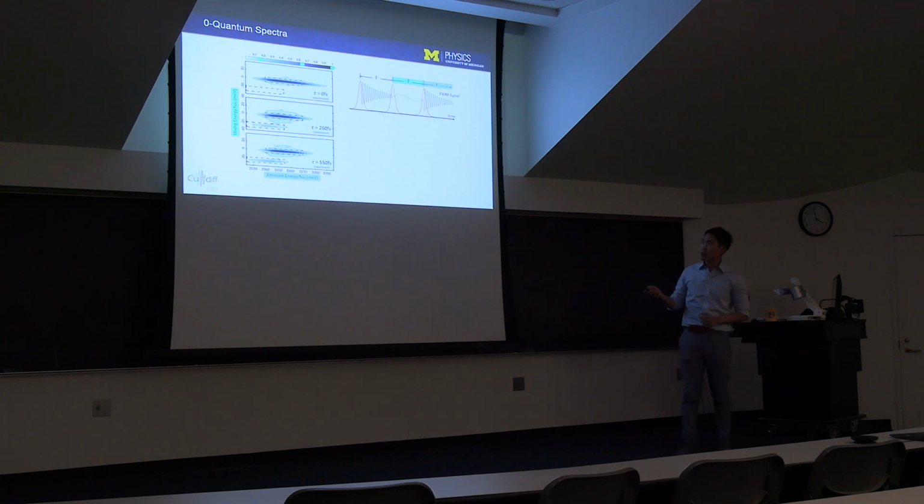And we can take a closer look by integrating the peak intensities over these dashed boxes. And what we find is that the sideband exhibits a long rise over 250 femtoseconds, which is really strange behavior in contrast to the usual exponential dephasing dynamics. And I want to emphasize that these curves reflect the dynamics of the interband coherences excited by the first pulse.